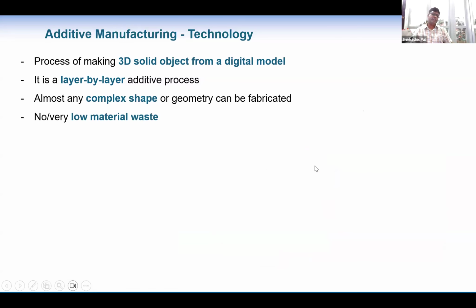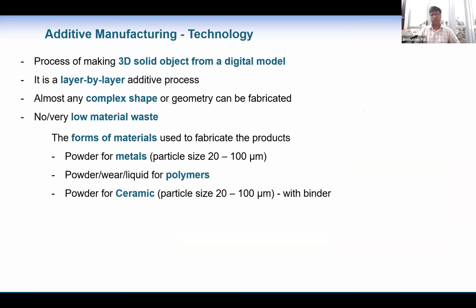In a powder bed process, as I told you before, we use powder material and whatever we need, we just melt and fabricate that portion, and the other part of the powder remains as it is. So that's why it's quite easy. We can reuse the powder again. The powder particle size, as I told you, can be 20 micron to 100 micron.